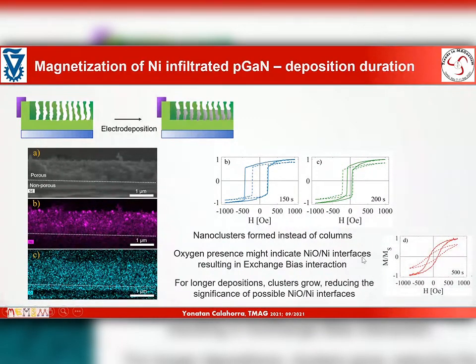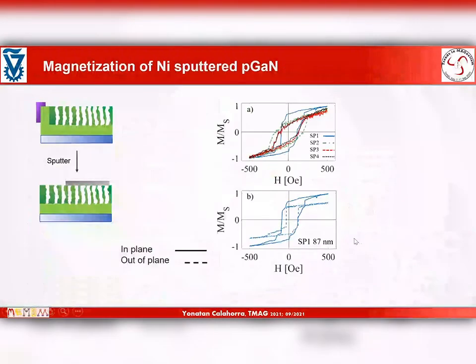And as we saw earlier, as more nickel is deposited, the overall weight of the nickel oxide is reduced, or the relative weight, and then we see less of these effects and more of the thin film-like properties. What about nickel sputtered porous gallium nitride? So this is still work in progress, but if we look at the thinnest nickel layers deposited, less than 100 nanometers, we see again